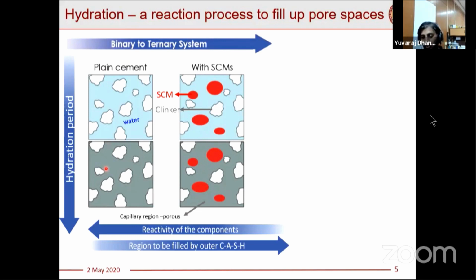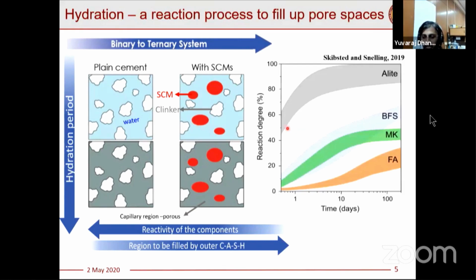Now we want to move towards blended cements, where a portion of the cement clinkers will be replaced by SCMs. Right? And what we know from literature is the reaction degree of the SCMs is much lower compared to your alite, which is a major cement component. So these are going to react much more slowly, which means the reactivity of the material goes down. So you have to cure more to get the benefit, or simply put in perspective of space, the region to be filled by the pozzolanic reaction increases, and which happens much slower.